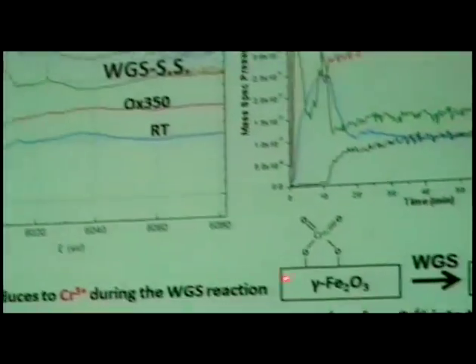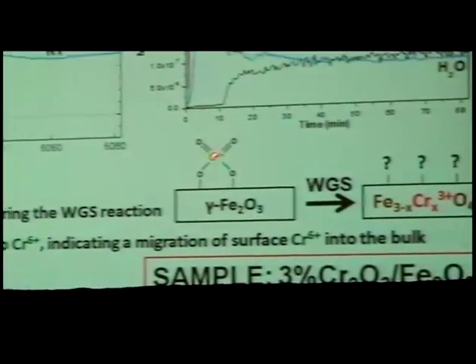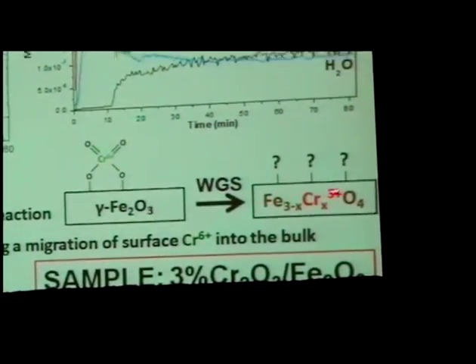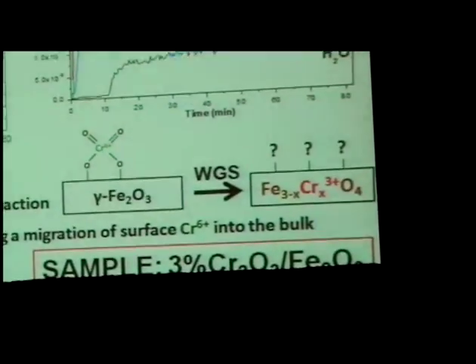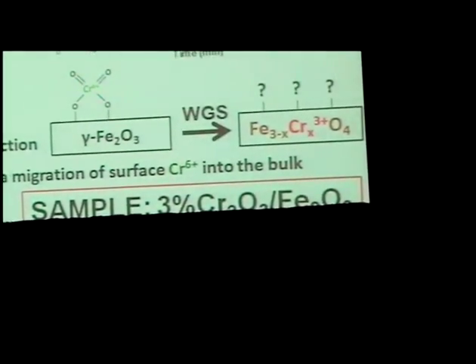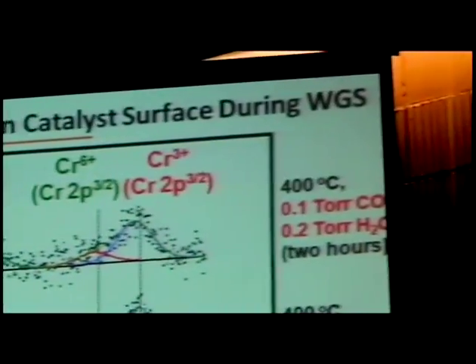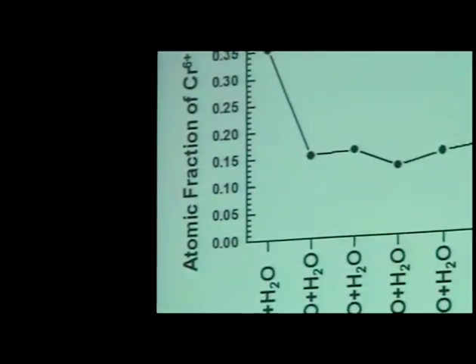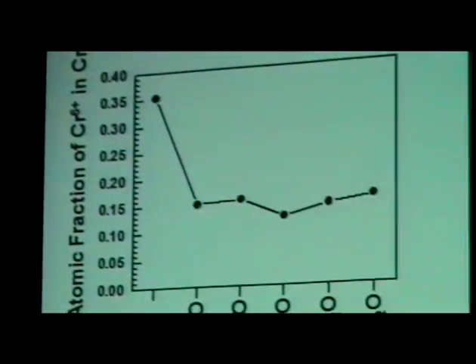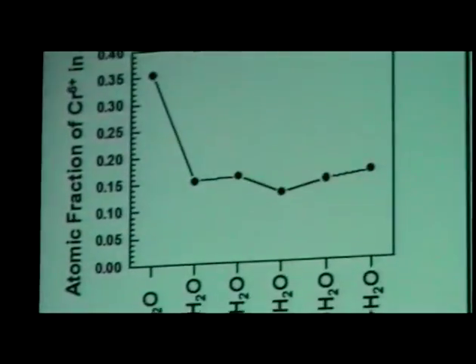And so we know we start off with the chromium on the surface. The chromium goes in. A lot of it is stabilized during the transformation of Fe2O3 to magnetite. But the question is, is there any chromium on the surface, and what is its oxidation state? And this is where we turn to Franklin Tao with his unique in situ atmospheric pressure XPS system that allows you to monitor the oxidation states of, in this case, chromium. Also looking at iron, but it's not necessary to show that.